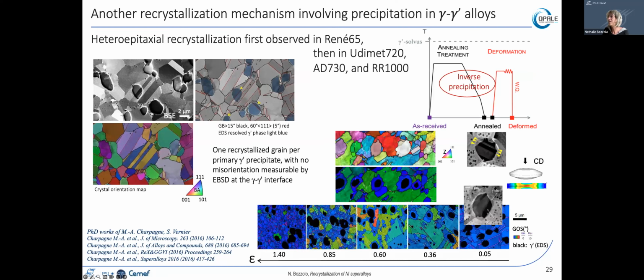And once you start deforming this system, these small volumes of the gamma-like phase start growing to produce a recrystallized grain, which embeds the pristine precipitate and keeps the orientation of the precipitates, because at the beginning, this phase transformation phenomenon, which occurs here, producing this small volume of gamma-like phase, actually leads to a crystal orientation for the gamma-like phase which is the same as that of the gamma prime precipitate.